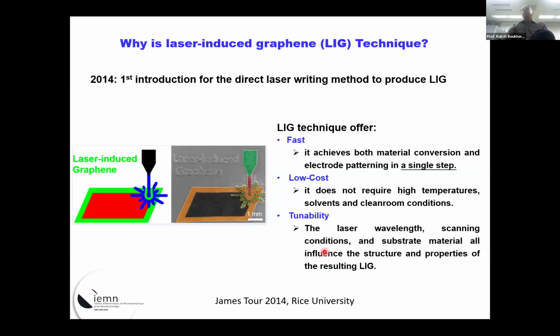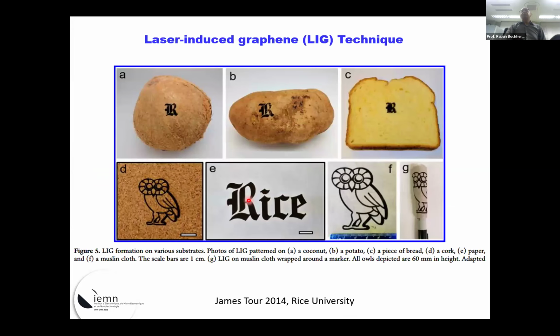The only thing one has to say is that although we can consider this very cheap, you also generate CO2, because you provide such high energy from the laser input that you burn your carbon-based material, so you generate quite a lot of CO2. This technique was initially discovered by, I would say, accident. It was not meant for writing graphene. It was graphene deposited on a polymer film, and the idea was to treat it with a laser to see if you could make much higher-conducting graphene.